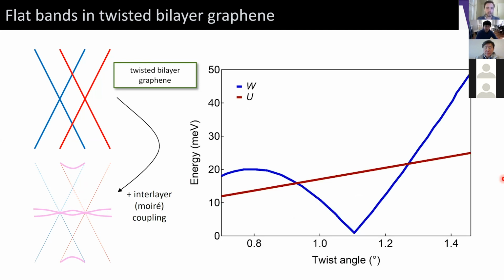Okay, so we can calculate then, for a fixed interlayer coupling strength, what the bandwidth of twisted bilayer graphene is as a function of twist angle. And we see that it actually tends to vanish around this so-called magic angle of about 1.1 degrees. When this happens, the kinetic energy of the electrons in the system is quenched, and the mutual Coulomb repulsion between electrons, which is mediated on this Moiré length scale, becomes a dominant energy scale in the problem.